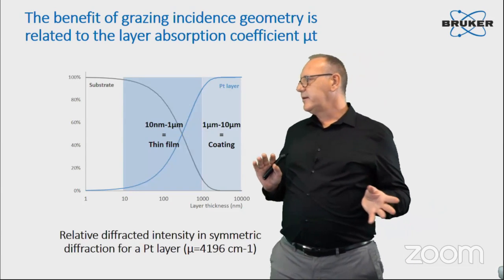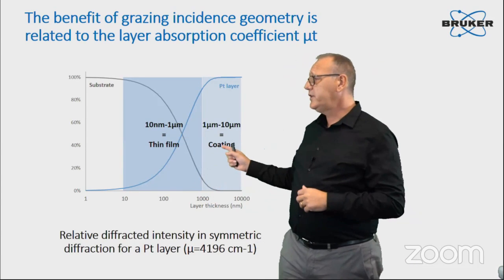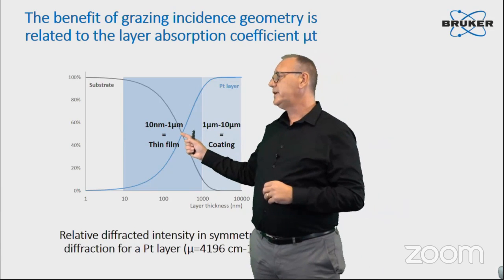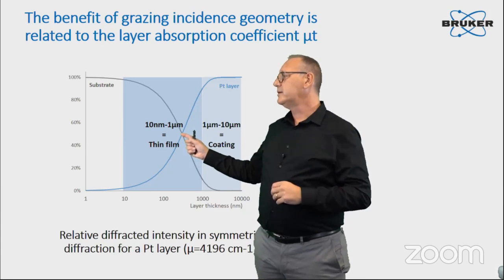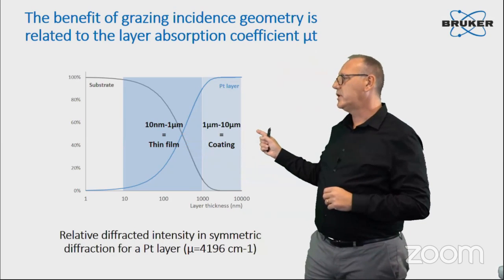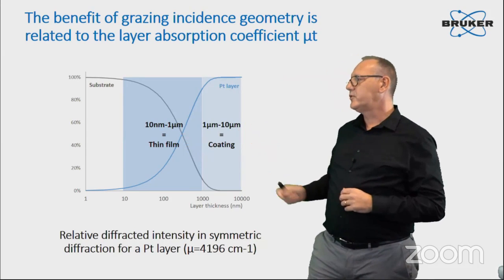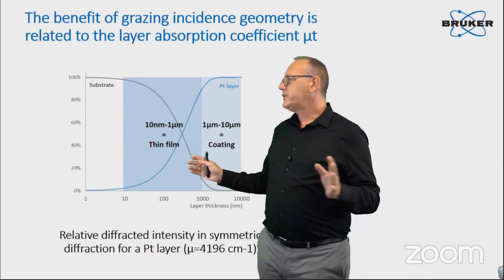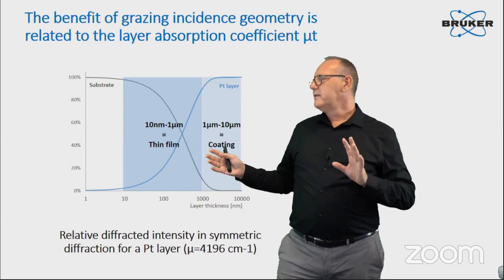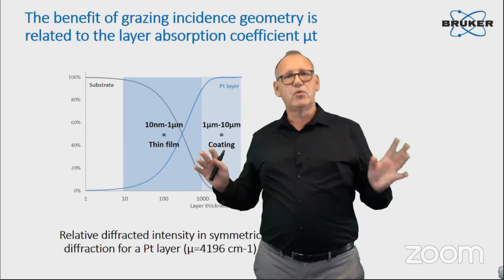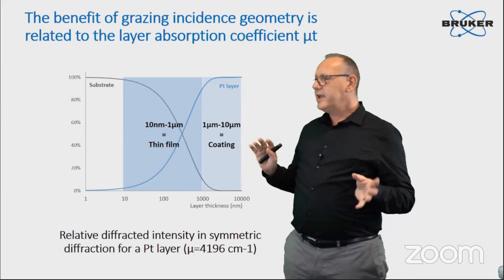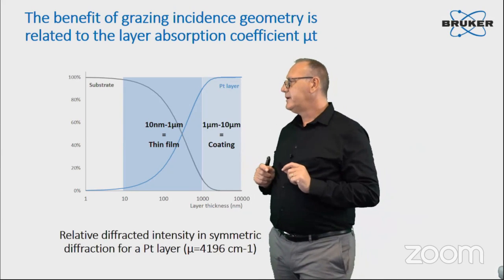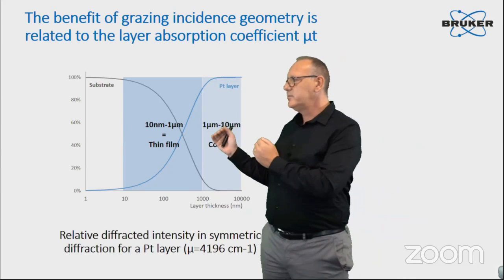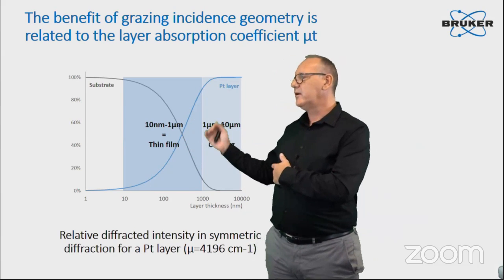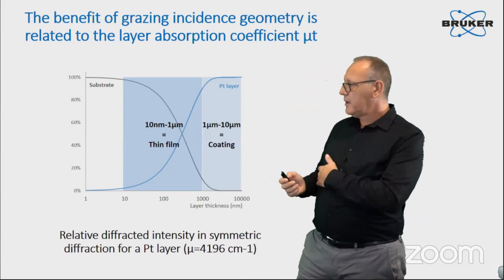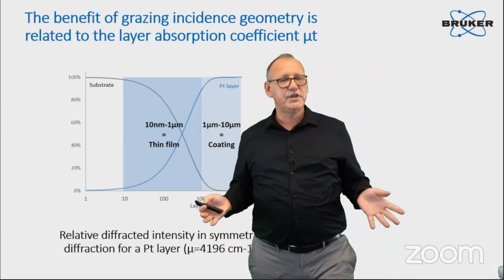Here we define an intermediate range, and actually this crossing point strongly depends on your material. If it's somewhere here for platinum, for an organic layer, it may shift much higher, so you may need to set up the GID much earlier. But in a range here for platinum between a few tens of nanometers to 1 micron, you would still be able to nicely identify your layer because you will have a mix of intensity between the two contributions. So this is what I would call the thin film regime.